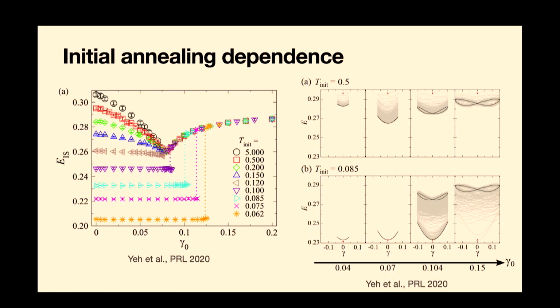Okay? And so now you can record the steady state energy, this particularly is the inherent structure energy, but that's not important here, as a function of amplitude, and the different curves here are different degrees of annealing as parameterized here by an initial temperature for the protocol by which you make the material. Okay? And so what you see is that the poorly annealed samples, where you've done a bad job of lowering the energy, after you've increased the amplitude, so if you increase the amplitude each time reaching a steady state, they all get to the same point. Okay, so at some characteristic strain, they all seem to have the same state because the energies are all identical. So you sort of strain annealed in some sense these samples. Okay, you've made them better in the sense of lowering energy.